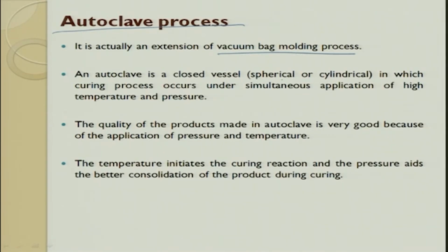Here it is predominantly thermoset. So it is a thermoset process. So you should also make sure that shrinkages, strength, all these things are taken care of. And the advantage of autoclave or all these vacuum bags is that you are trying to avoid resin rich regions. If you avoid resin rich regions, the weight goes down, the quality enhances. The quality of the product made by autoclave is very good as compared to all other processes.